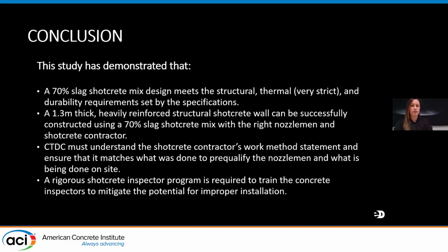So in conclusion, this study has demonstrated that a 70% slag shotcrete mix design meets the structural, very strict thermal and durability requirements set by the specifications. A 1.3 meter thick, heavily reinforced structural shotcrete wall can be successfully constructed using a 70% slag shotcrete mix with the right nozzleman and shotcrete contractor.